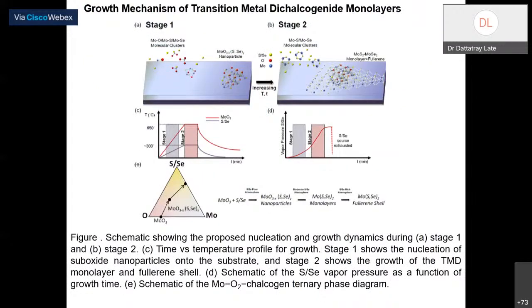So see, this is a simple growth mechanism again. Chemical vapor deposition: you have MoS2 or MoSe2 depending upon what you have taken. You have cluster formation, you have conversion of MoO3 into sulfur or selenium nanoparticles, and these go and sit on the surface of the substrate. When the evaporation point is reached, in stage 1 and stage 2, you will have MoO3 converted into MoSe2 or MoS2 depending upon which second salt or precursor you have taken. So you'll get the layer again.